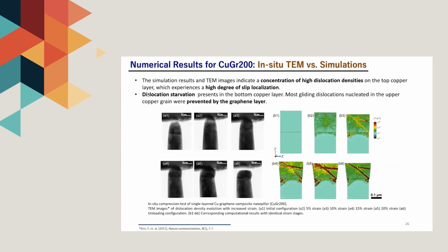The experiments on the left side show the concentration of high dislocation density on the top copper layer. This is because the shape of the top layer, which is fabricated with some curvature, induces a high degree of slip localization.